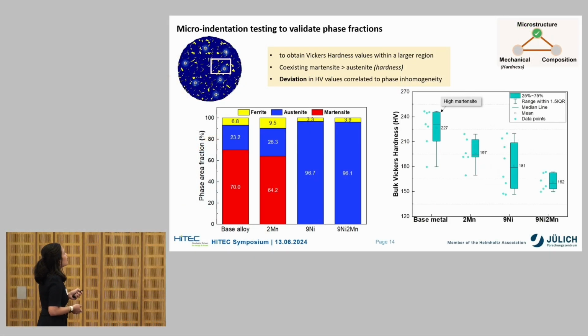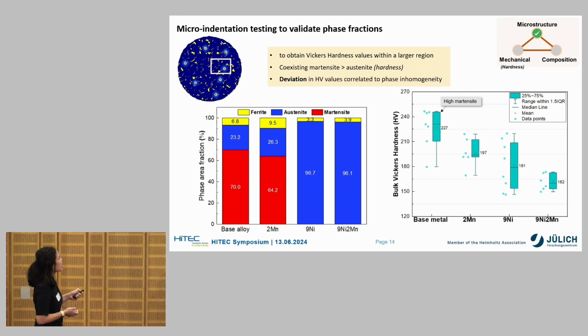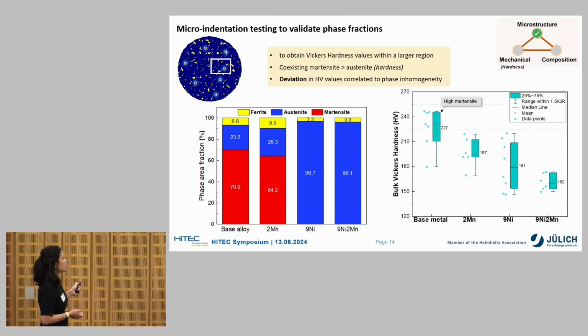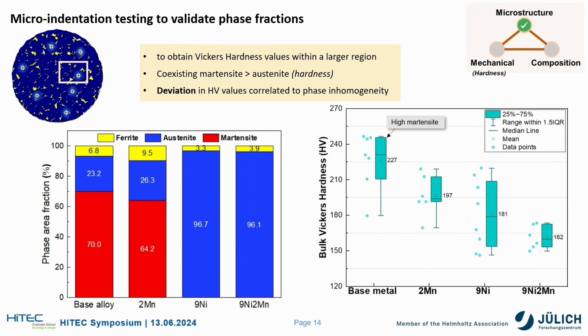Results have shown that the base metal, as you can see here, has the highest martensite fraction. And here, it has the highest hardness value attributed to this martensite fraction, followed by the 2Mn alloy. Interestingly, for the 9Ni, although we saw beforehand that it might be predominantly austenitic here, we see a high standard deviation, which might indicate that the phase is highly inhomogeneous. Finally, for this 9Ni2Mn, we see low hardness value and low standard deviation, indicating that the microstructure was homogeneously austenitic.